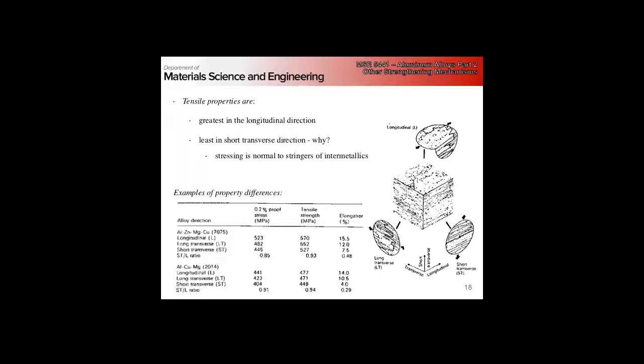Well, sometimes you can. If we have an aged alloy, we can form it, but then we would have to solution heat treat, quench, and age again. That we can do, but there are some systems where we're really hindered, because treatment like that could also grow grains, depending on what the system is. In these two systems it will be fine, but in other ones the subsequent thermal processing will grow our grains to a size that we may not be able to have, or we may lose an important texture.